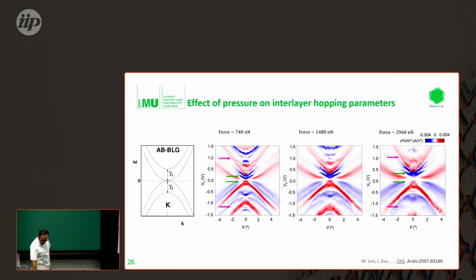The other thing which we can also do in this technique is apply pressure. Because we have such a narrow tip region, we can press into the device, and we can apply pressures up to some gigapascals. So this measurement here on the right, this 3,000 nanonewtons that we apply as force on the device, corresponds to something like 1 gigapascal of pressure. So with this, one can of course also change the band structure of the material.